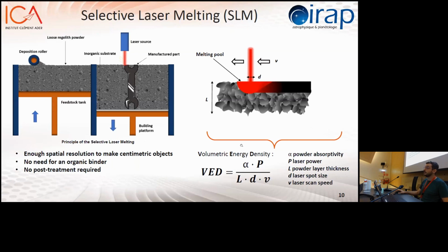Because if I don't bring enough energy, I will create some lack of fusion and so porosities. And it's the opposite if I bring too much energy to the material: I will vaporize some content and I will also create some porosities. And that's not a good thing for the mechanical properties. So why use this method rather than another? It's because of two main reasons. There's no need for an organic binder and no post-treatment neither, like debinding or sintering. And so that's a lot of payload you can save for other experiments during your lunar missions.